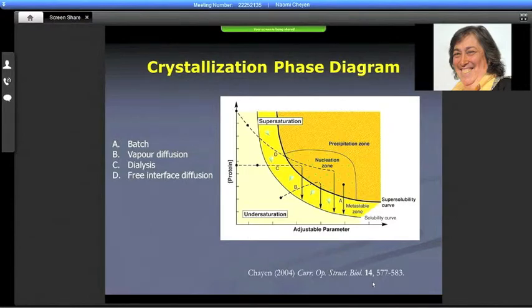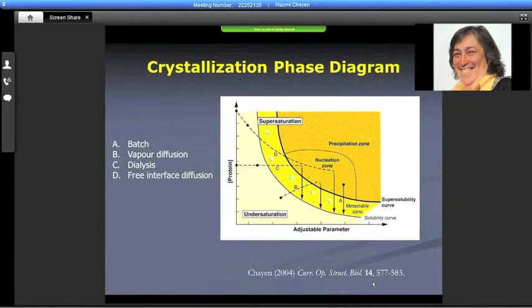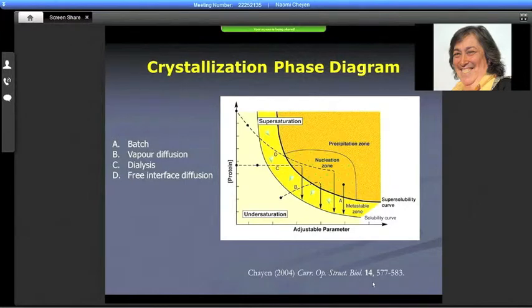For example, with vapor diffusion, you can see it starts as undersaturated and has a self-screening process, traveling through the phase diagram where protein concentration and the adjustable parameter both go up. In an ideal experiment, the system reaches the nucleation zone, and once just enough nuclei have formed, it moves into the metastable zone as protein depletes from solution. Theoretically this looks very well, and in 10–20% of cases it happens. But more often than not it doesn't happen and we have to intervene — that's what I mean by guiding.